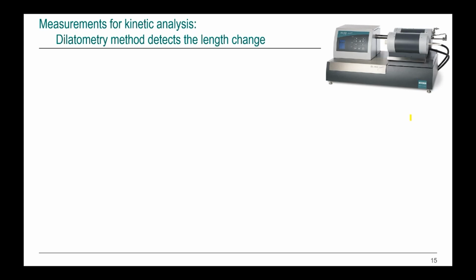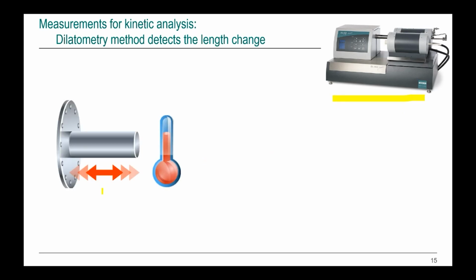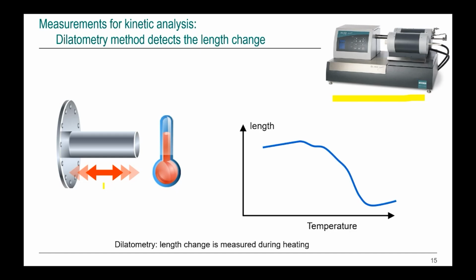And now let's see what happens above 700 degrees C. We take our dilatometer, we measure the change of length of our ceramics. We measure the densification process. Here is our result. We have originally the thermal expansion. After that, there is a sintering, so the reducing of the length of our material. And after that, we have thermal expansion after the sintering process for the product.